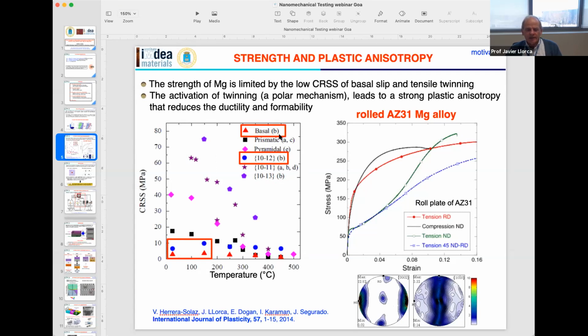Basal slip along the basal plane, and if you want to accommodate deformation along the z-axis, you have to have twinning. And twinning is a polar deformation mechanism, so it only occurs when shear deformation extends the z-axis of the lattice. So imagine that you have a rolled magnesium alloy like this one that has a very strong basal texture. It means that the basal planes are parallel to the rolling direction. Then if you do mechanical tests of this material along different orientations, you may have a very strong anisotropy. If you load the material in tension along the rolling direction, that is the red curve, or in compression along the normal direction, you cannot activate twinning.